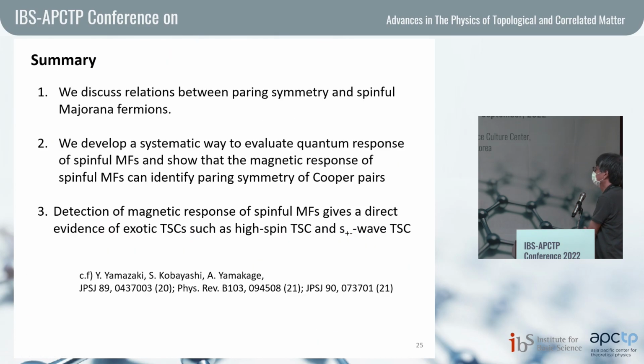So let me summarize my talk. We discussed the relation between the pair symmetry and the spin-full Majorana fermions. And we developed a systematic way to evaluate the quantum response of spin-full Majorana fermions, and showed that the magnetic response of spin-full Majorana fermions can identify the pair symmetry of the Cooper pairs. And actually, the detection of the magnetic response of spin-full Majorana fermions gives direct evidence of exotic topological superconductors, such as higher spin topological superconductivity or S plus minus wave topological superconductivity.